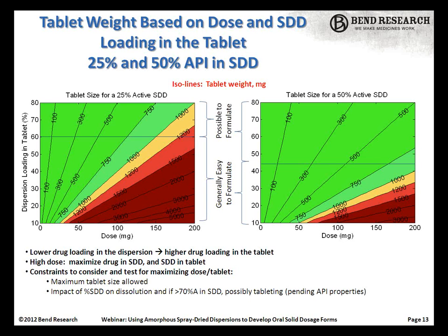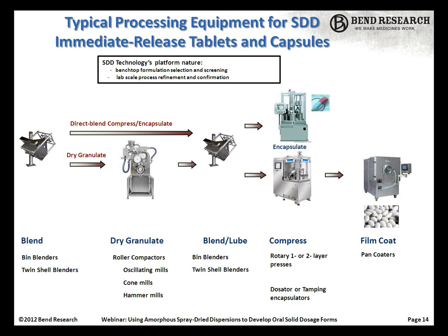So I'm going to talk a little bit more about the process here and then how we go about developing formulations from inception up through at least clinical manufacturing at pilot scale. One of the key things to note here is really our objective is sort of to do no harm. Chris was mentioning that we've put a lot of effort into forming a stable, well-performing drug product intermediate. And our goal then is to deliver that effectively as if it were a suspension. That's our ultimate goal in almost all cases. There are some exceptions where we'll get too fast of an onset and want to go a little bit slower. But generally speaking, we try to get disintegration and dissolution as fast as possible to make sure that we don't miss any absorption windows where the bile salts and the highest absorption occurs.